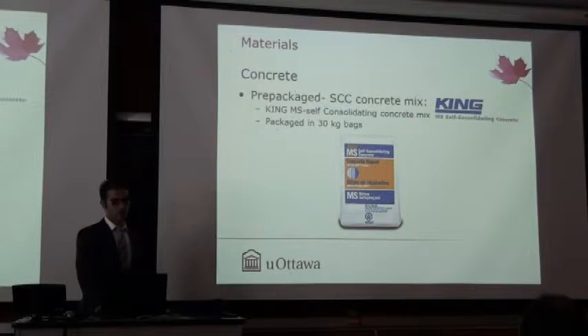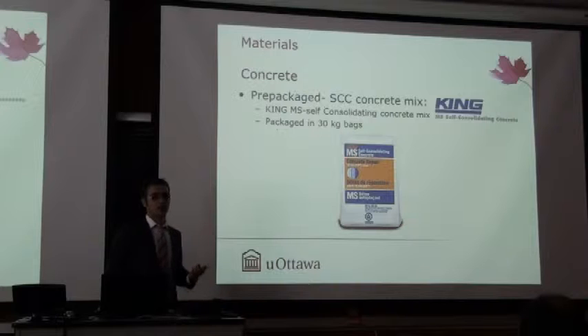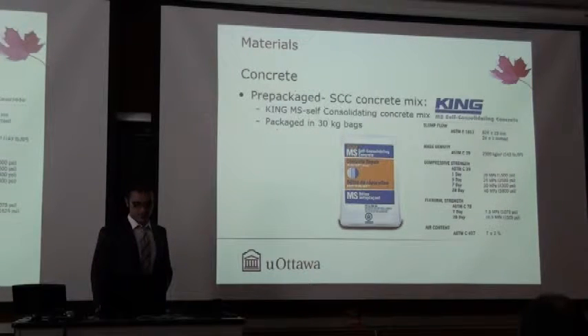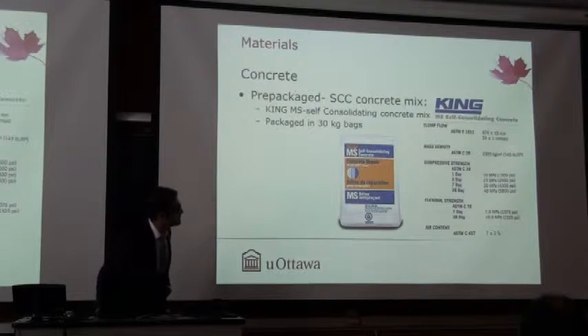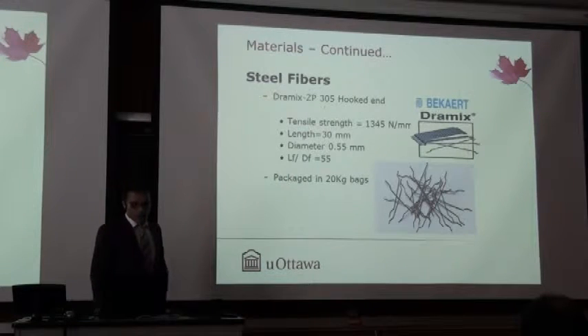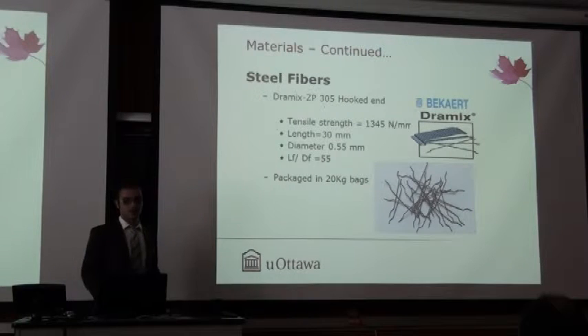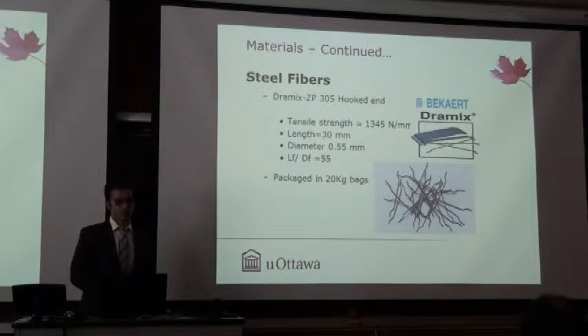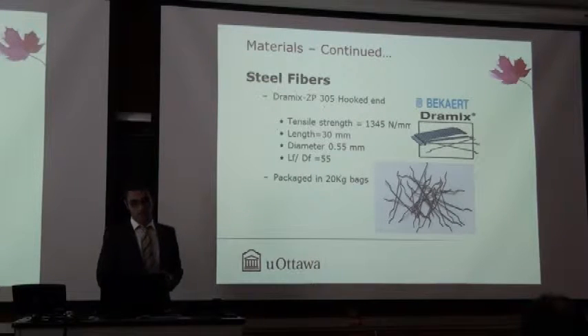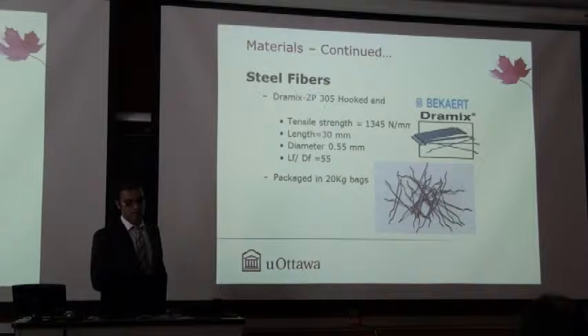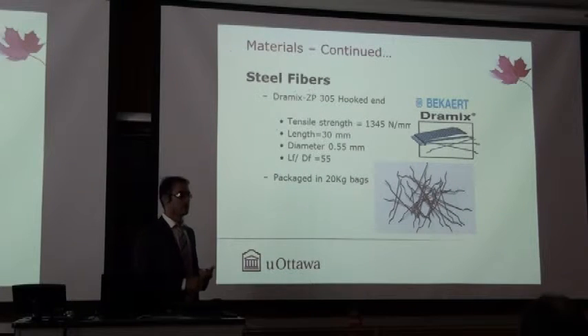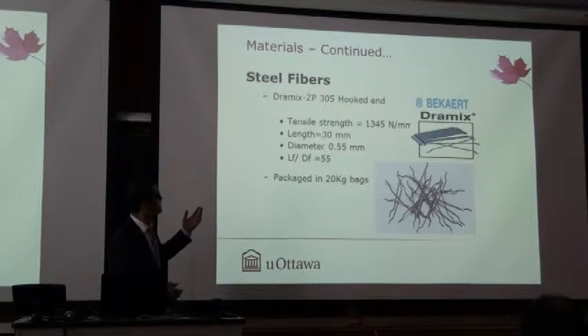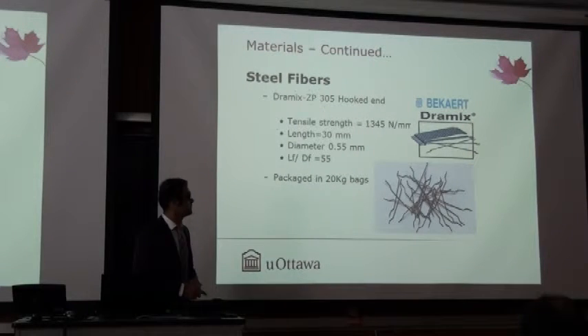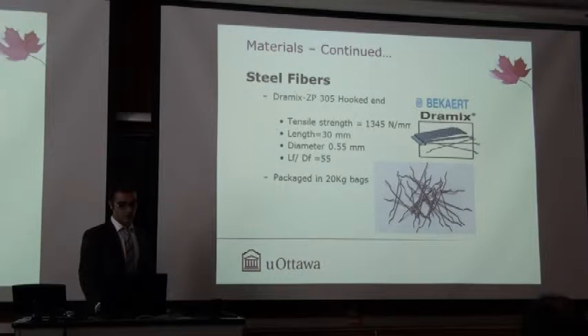We used the King MS SCC concrete mix, which came in 30 kilogram bags. It's pre-mixed, so it's pretty easy to work with. We basically add water to it and cast the beams. Here are some details of the mix. We used hooked end steel fibers, Dramix ZP305 type. The tensile strength is pretty high, 1,345 MPa. The length is 30 millimeters and the diameter is 0.55 millimeters, which gave us an aspect ratio of 55. It also came in packages of 20 kilograms.